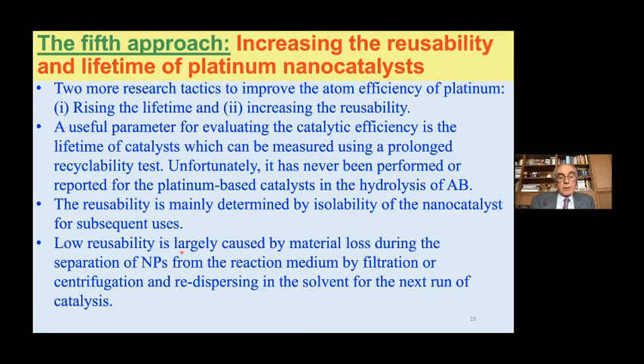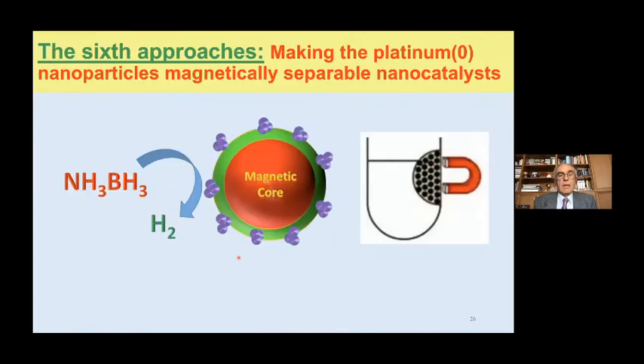Low reusability is because of material loss during the separation of nanoparticles from the reaction solution, either by filtration or centrifugation, and redispersing in the solvent for the next run of catalysis. During all these processes, materials will be lost, certainly unavoidable, I should say. Okay, how can we avoid that? Making the nanoparticles magnetically separable. That will be nice. So that is the sixth approach, actually, making the platinum nanocatalysts magnetically separable. So nanoparticles can be supported on the surface of a magnetic core, and that means the nanocatalyst will be separated by using an external magnet.